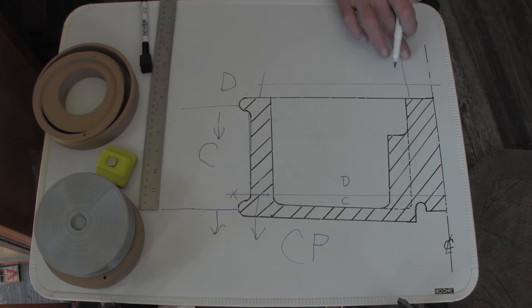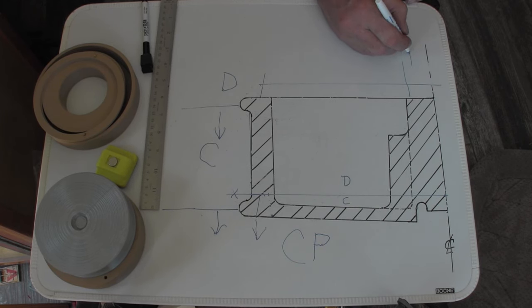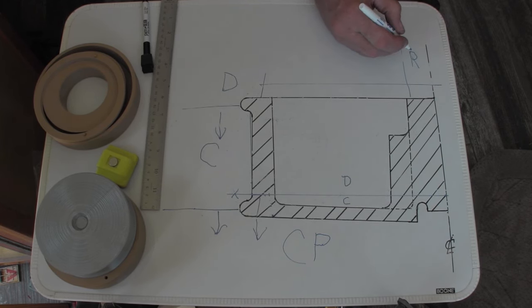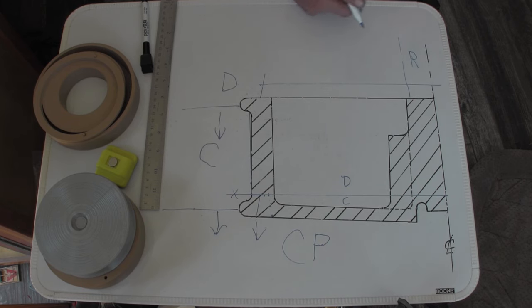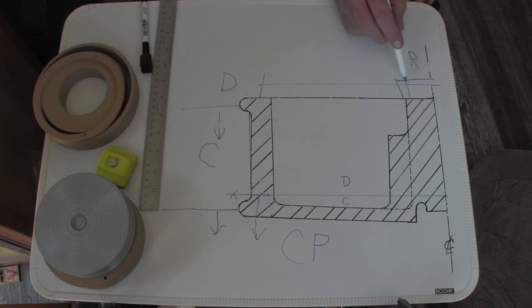And, riser's there. I hate writing backwards. You could eliminate that riser. They got what they call a chill. It's basically, since this is an iron casting, you can use a piece of steel or a piece of iron that's flat, and that chill is rammed up in the mold, so it would be drafted like this in here.